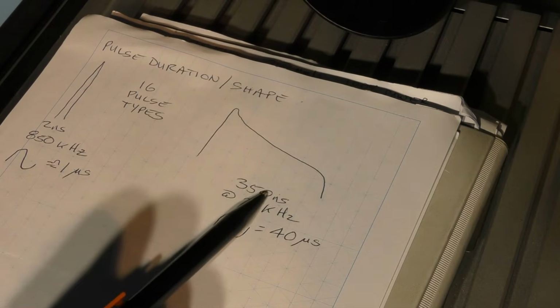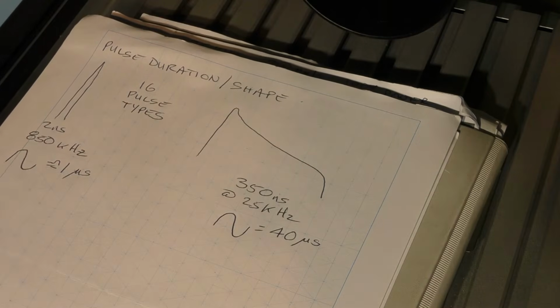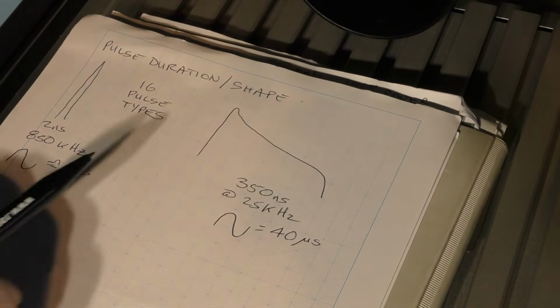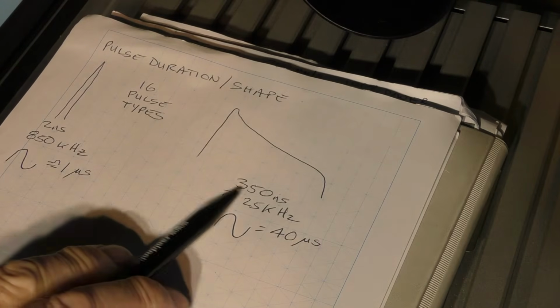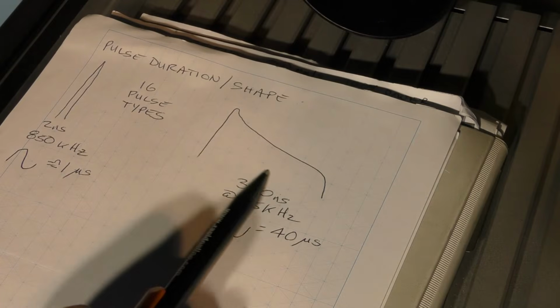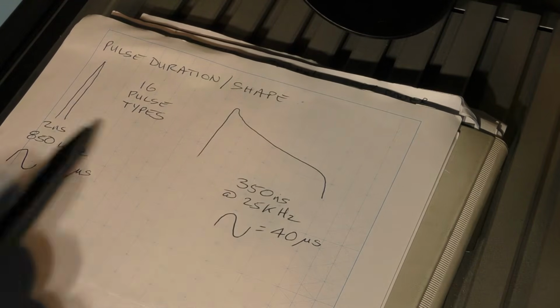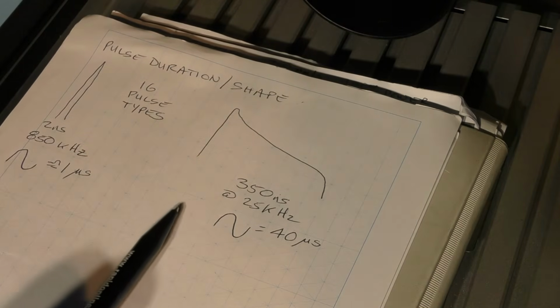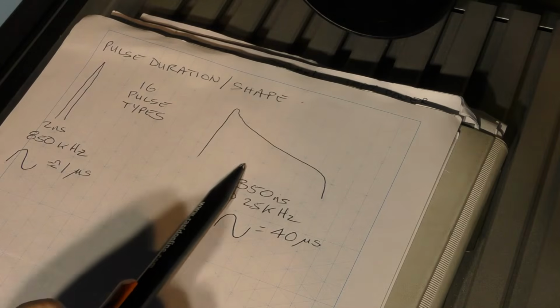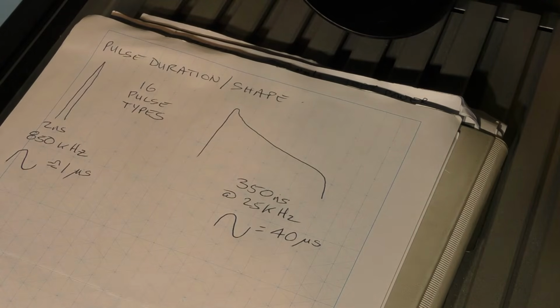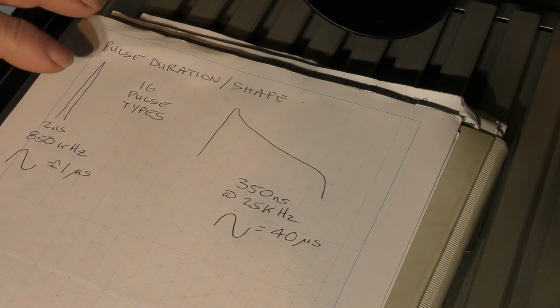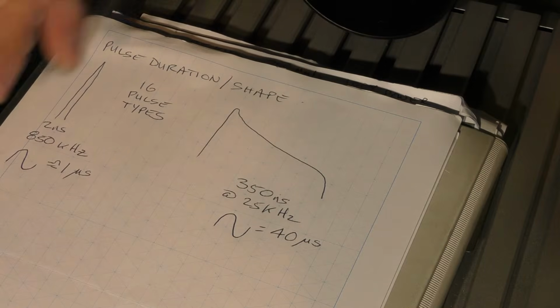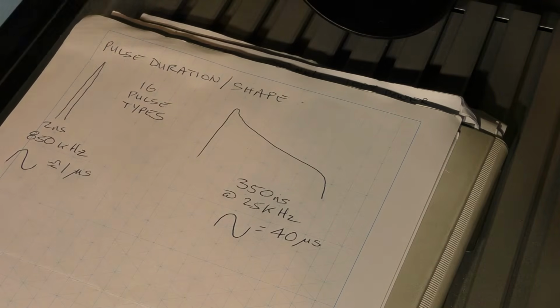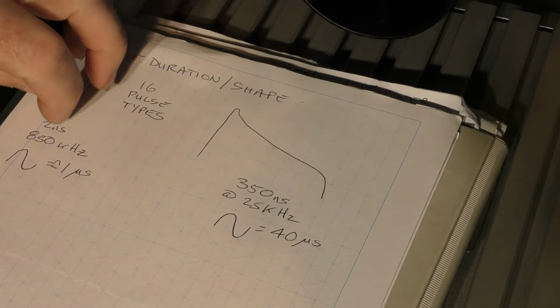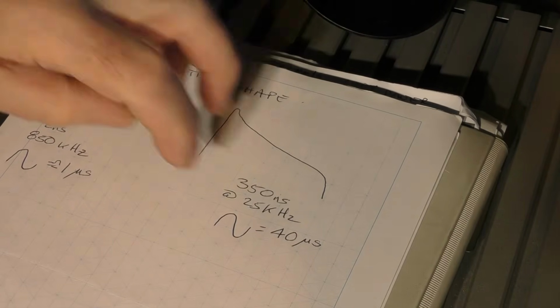But the pulse is 350 nanoseconds. This pulse is 2 nanoseconds. So in terms of pulse duration, this one is effectively about 170 times longer than that one, but its repetition rate, the number of times that pulse gets put down, is 40 times slower. And this is the strange balancing act. What I'm first going to do is just quickly show you in a sample patch the difference between these two, so you get a feeling for the damage that these two extremes can do to the material.